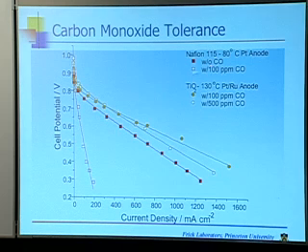We take our cell and now take the temperature up to 130 degrees. And we have added in some titanium into our membrane now so that we can do that. And we get the solid orange curve right there. And you'll notice that not only does it obviously outperform the CO poison curve, it actually is still outperforming the normal temperature Nafion curve in the absence of any CO.